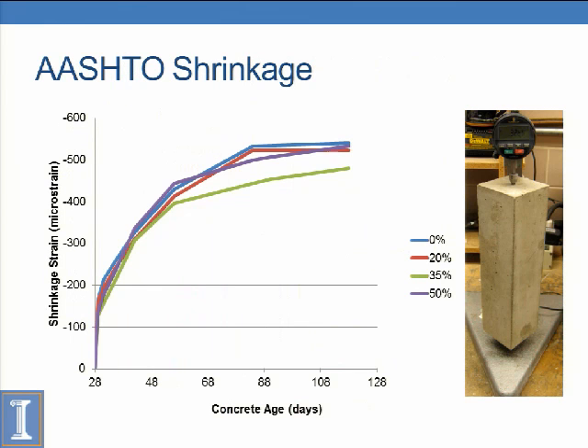So now looking at concrete shrinkage. This test, we have a beam with gauge studs in the end, and we have it in a humidity-controlled room at 50% relative humidity. So at that humidity, you'll lose moisture, your concrete will shrink. So it's an important property to know in the real world, so you avoid shrinkage cracks, things like that. For the most part, our shrinkage, we concluded, was unaffected by the FRAP. 35% was a little bit lower here, but you can see the 50, 20, and 0% FRAP mixes were all about the same shrinkage rate after 90 days.